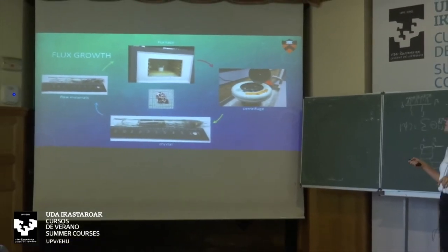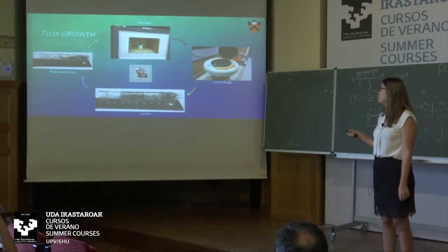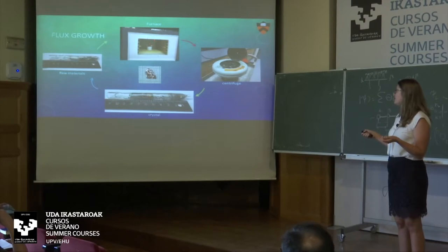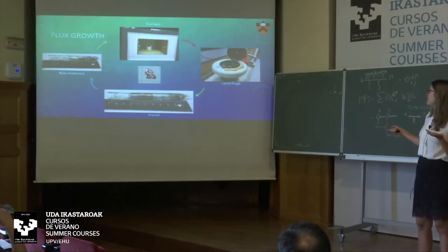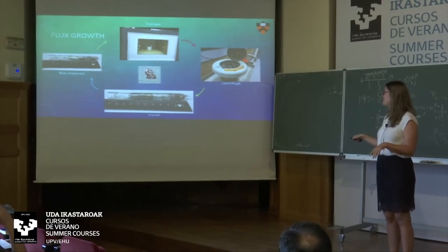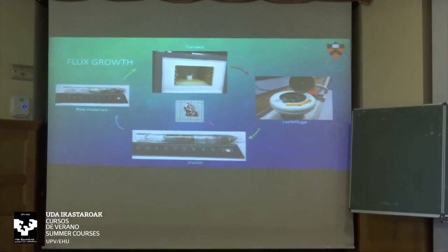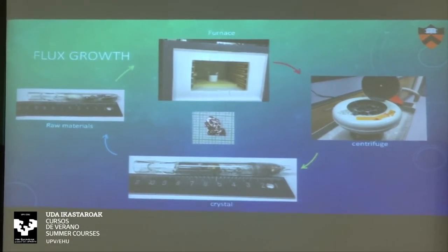Here's the process in my lab. We're growing a telluride out of a tellurium self-flux. Here's the tube before with solid tellurium chunks and a tiny amount of the other elements we want to make. We put it in a furnace in a crucible standing upside down, heat it, and slowly cool it until a temperature where tellurium is still liquid. We take it out with tongs and put it upside down in a centrifuge — which was about 100 bucks on eBay but works great. We centrifuge down the liquid, and in the tube you can see the filter area and here at this end are your red shiny crystals. If you don't find crystals, you can put it back and try a different temperature profile.